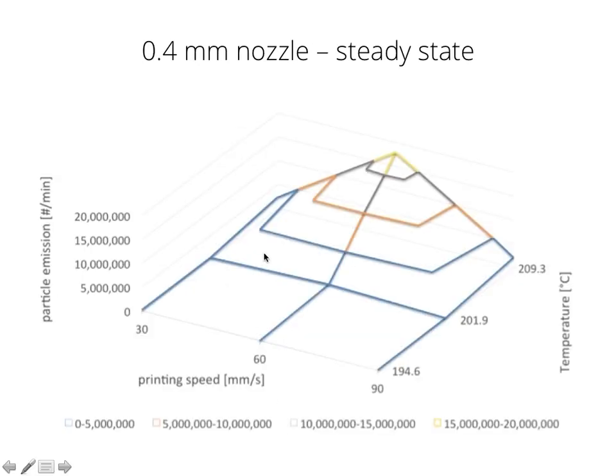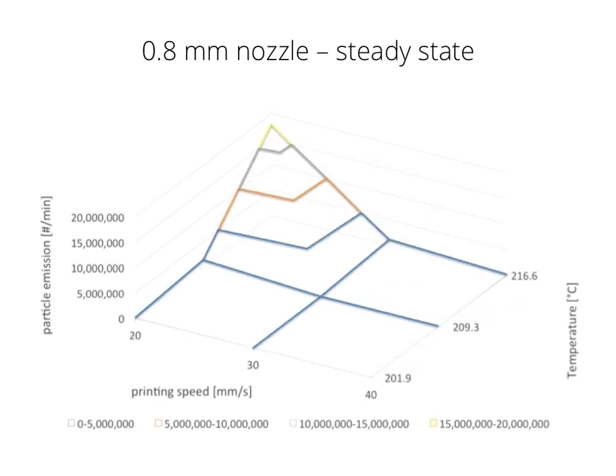The exponential growth is hard to visualize well in the previous graphics, so I made a 3-dimensional diagram right here, so you can see a bit better how extreme these are. For the 60 millimeters per second, our highest particle emitter for the 0.4 millimeter nozzle at a steady state, you can see that you have a very sharp increase, while the 30 and the 90 millimeters per second are not such high particle emitters. And the same goes for the 0.8 millimeter nozzle.